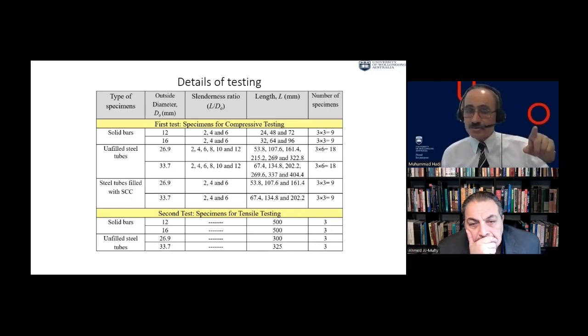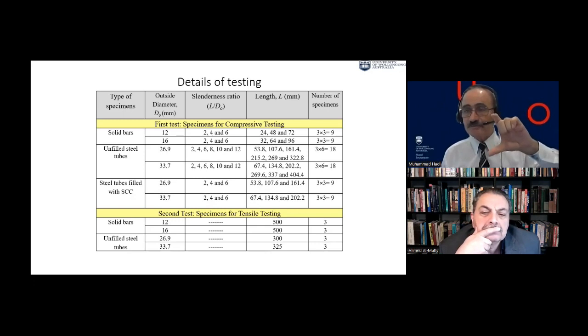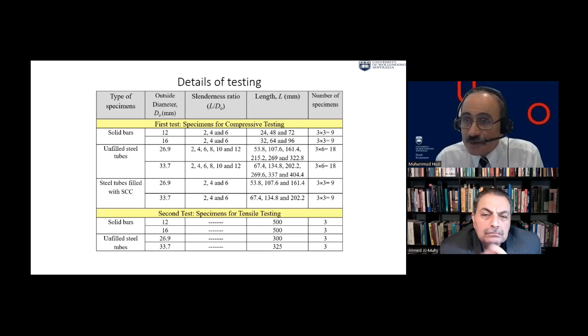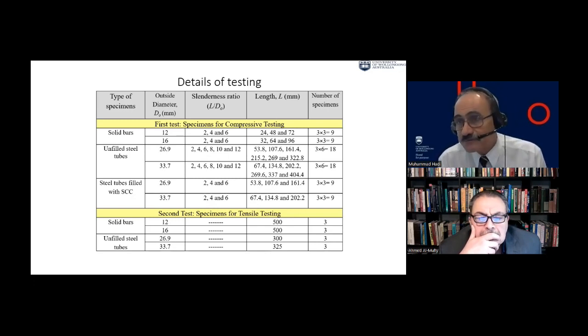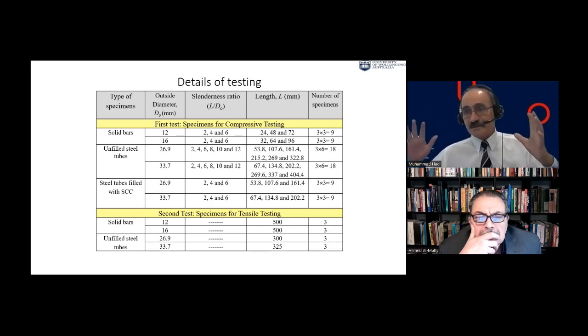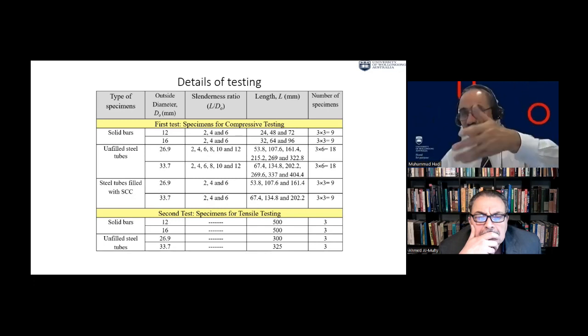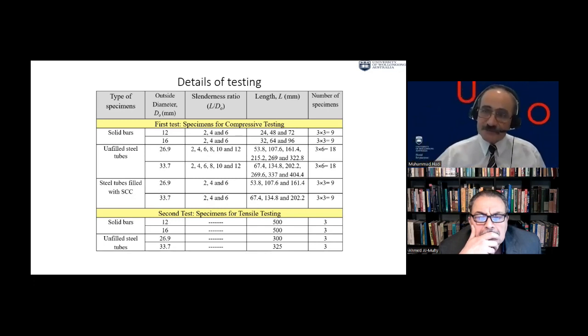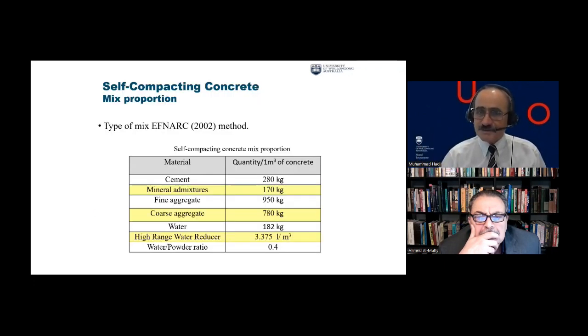Whereas when it comes to compression, there is the problem of buckling, pi squared EI over L squared. Because you have this problem, we had different L by D ratios, length to diameter ratio, to see what is the effect. And then we did those empty and full. So you can see this preliminary testing, you can see the size of the test. You have, I don't know, maybe 70, 80, and of course we repeat everything 3 times to have the average. So this is the idea.